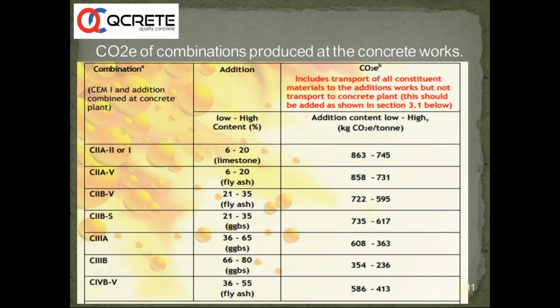Here you can see in this table, when we are adding OPC, there is about 900 kg per cubic meter of embodied carbon dioxide. When we are talking about fly ash addition between 21 to 35%, the embodied carbon dioxide is around 722 and 735 when we are talking about GGBS. So what the table is saying is, if you want a really significant reduction in carbon dioxide, then you need to probably move to about 36 to 65% of either GGBS or fly ash.